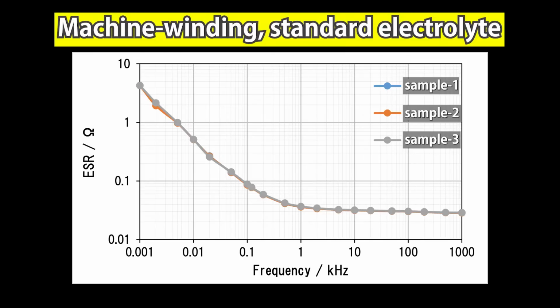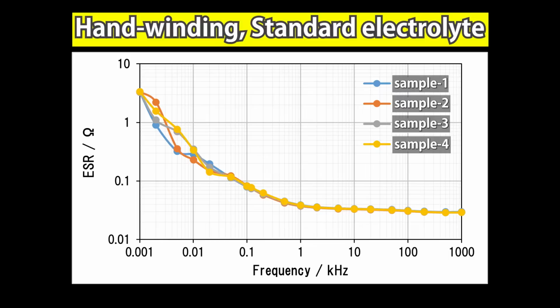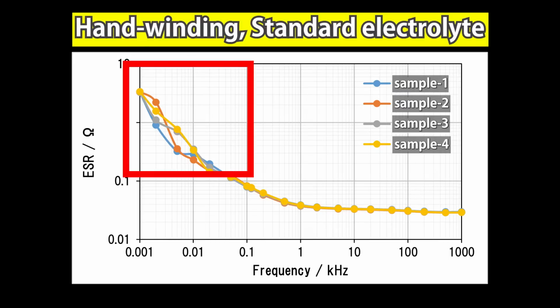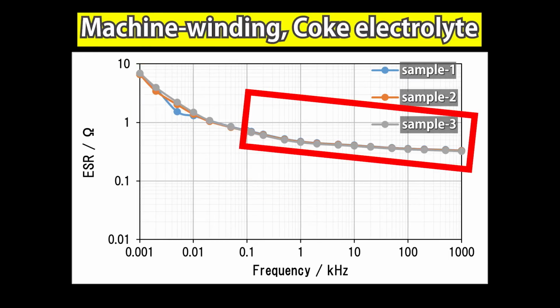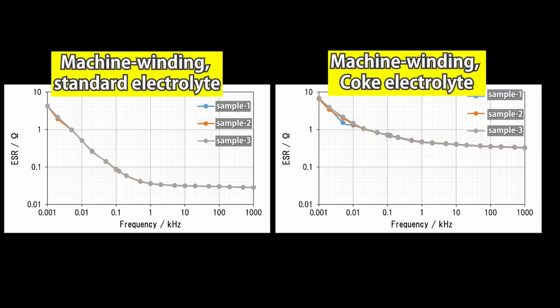Machines are really precise. The ESR of the ones I wound manually varies at lower frequency. It seems the winding ability affects the ESR. As for the Coke electrolyte capacitors, ESR at 1000 kHz is 350 milliohm. It's quite high, about 10 times the standard electrolyte capacitors. When you actually use the Coke capacitors, the performance will be extremely affected by ESR, I suppose.